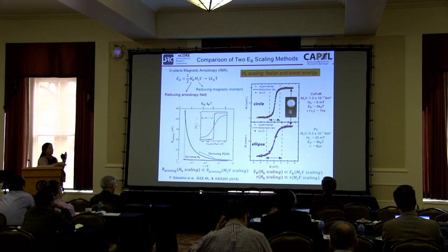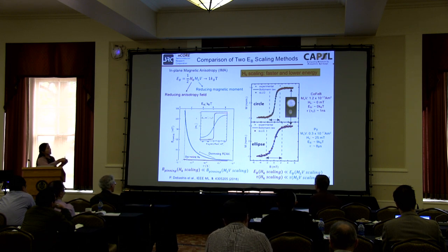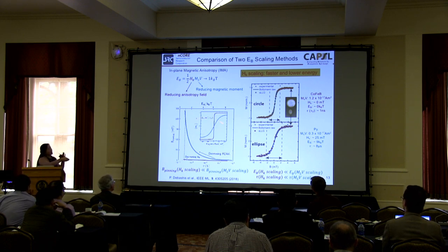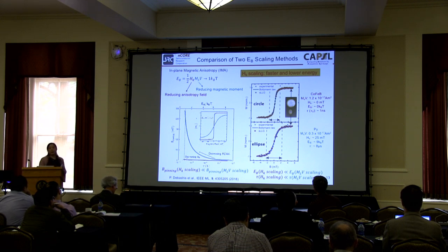One thing that I want to point out: depending on the application you are looking for, the pinning field will be different between these two methods. For example here, I don't know why the thing is not showing clearly, both of these curves are for the 1 kT magnet, but the red one is when I use the HK scaling method, and the blue one is using the MSV scaling method. You see the pinning field, to really pin down the magnet in a certain direction, requires a much larger pinning field when I do the MSV scaling. And so again, depending on the application, you may want to pin down the magnet at a different pinning field. So you will need to pick which method is more suitable for the application you have in mind.